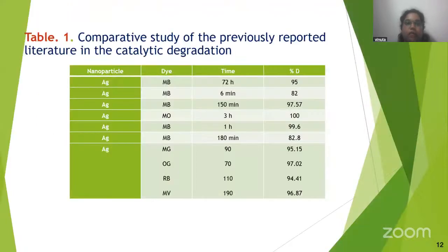Next is the comparative study of the previously reported literature on catalytic degradation. Various dyes were used for the degradation process: methylene blue, methyl orange, malachite green, orange G, rhodamine B, and methyl violet were already used. They used different time intervals for the degradation, and the efficiency is also good, as they already achieved more than 80%. Because of that, we selected some dyes and thought of doing catalytic degradation, because silver nanoparticles are already showing good results in catalytic degradation.